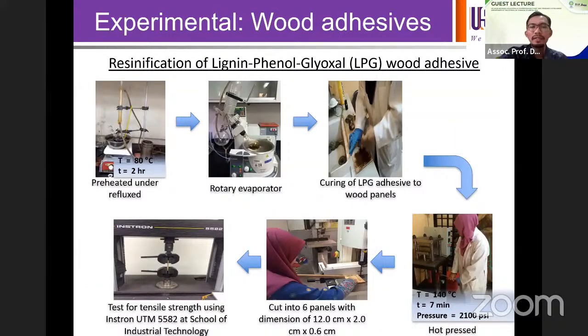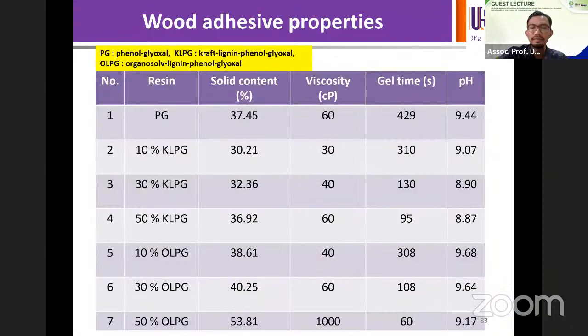After we have done the resinification, we concentrate it to make sure that the viscosity of the resin is slightly better. And we apply it on the plywood. After the application to the plywood, we hot press it and cure it, and it forms a panel. This panel will be cut into small pieces with a fixed dimension to follow ASTM or Japanese standards before we proceed with the tensile measurement.